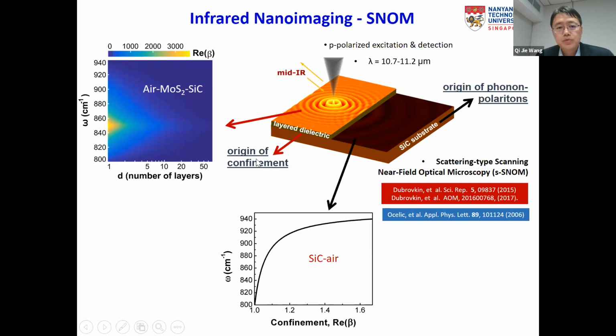And silicon carbide air interface does support the Phonon-Polariton, but as you can see, the confinement factor is very low, less than 2. However, by just simply put MoS2 on top of such structure, we can significantly achieve highly confined Phonon-Polariton with a factor of a few hundred times.